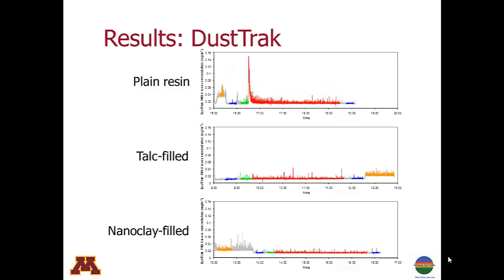When we look at the dust track data during the shredding periods, we can see that the mass concentrations measured were essentially the same as the background mass concentrations for all three test materials, except at the very beginning of the measurements with the plain resin, which was the first resin we tested, when we saw a spike in concentration at the very beginning of the shredding period. This spike is probably due to the granulator having some large particles from a previous study attached to its blades that did not come off until we started shredding our test plaques. We can see that concentrations fall back down to background levels very quickly following the spike.